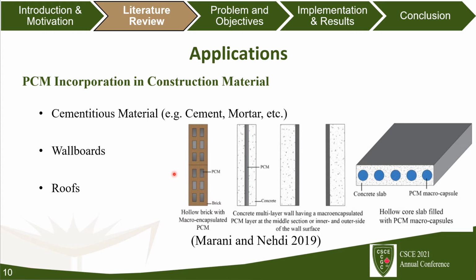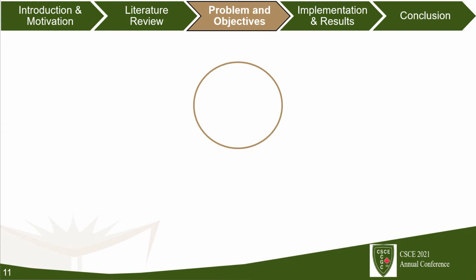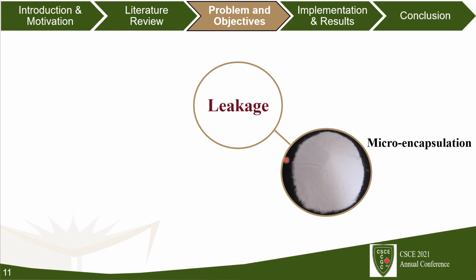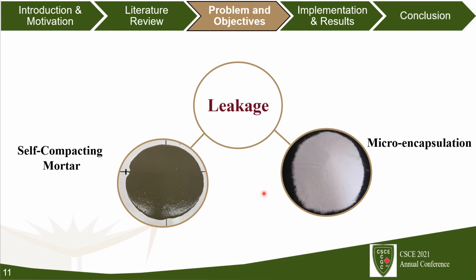masonry brick walls. However, one of the main drawbacks of adding phase change material to concrete is the reduction in mechanical properties induced by paraffin leakage and voids induced by broken phase change material capsules during mixing. To reduce leakage and prevent direct contact with construction material, we use microencapsulation. Also, we used self-compacting mortar to lower yield stresses and reduce the risk of fracturing the capsules.